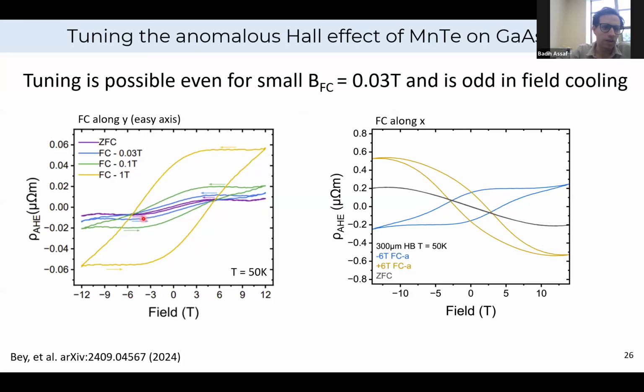Without field cooling, our anomalous Hall resistivity looks like this purple curve that I'm showing here. So essentially, there's nothing. And then as you ramp up this field cooling magnetic field, you start to open a hysteresis loop, and the hysteresis loop grows bigger and bigger until you consistently get something that looks like a minor loop for fields as large as 6 or 7 Tesla sometimes. The highlight here is that a field as small as 0.03 Tesla allowed us to open a loop, and that the polarity of the field cooling is interesting. The direction of the loop was actually odd under the direction of field cooling.